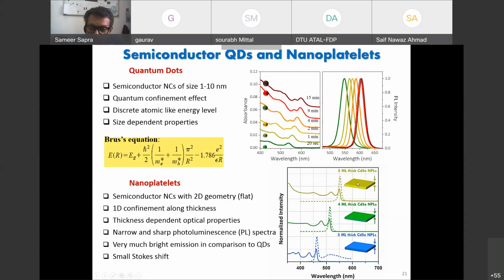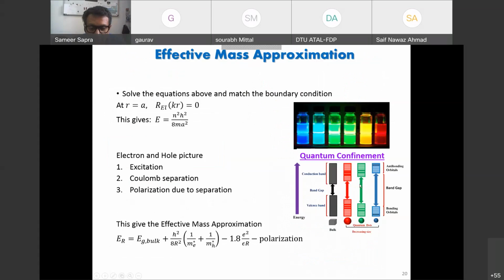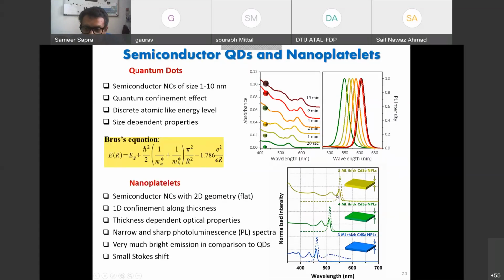So the moment you have very pure 5 monolayer thick nanoplatelets, you see the emission is very sharp. The emission full width at half maximum is less than 10 nanometers. Here, it's less than 30 nanometers. So all these emissions are much sharper than the spherical quantum dots.